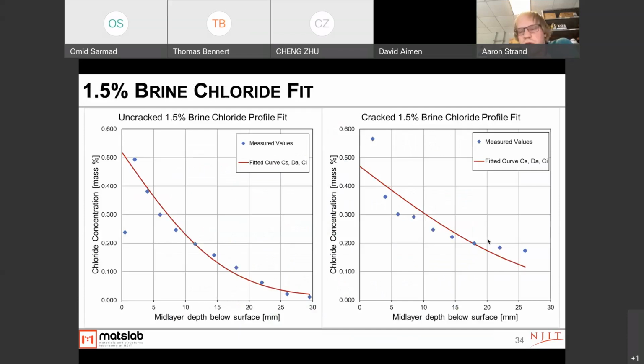What was, I think, one of the most interesting things about this data is that when we did the curve fitting in order to figure out the diffusion coefficient, for an uncracked specimen, the curve fit fairly well, as to be expected. And in the cracked specimen, where we have the dual mechanism within our powder of diffusion from the top, and also out from the crack, and from the crack itself, the curve fit is not very well aligned with the actual measured data values. This indicates that when we start getting into crack situations, other methods might be needed to figure out the diffusion coefficient, or how the chlorides are actually ingressing, as the more typical diffusion coefficient isn't likely to be as applicable to these situations.